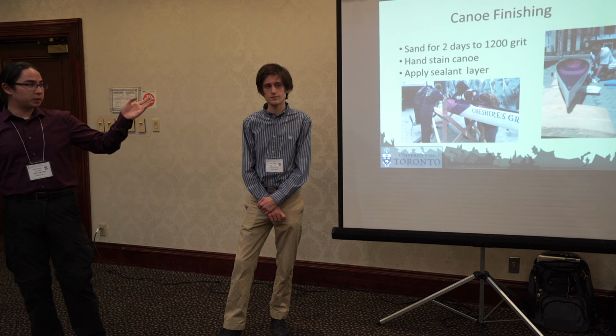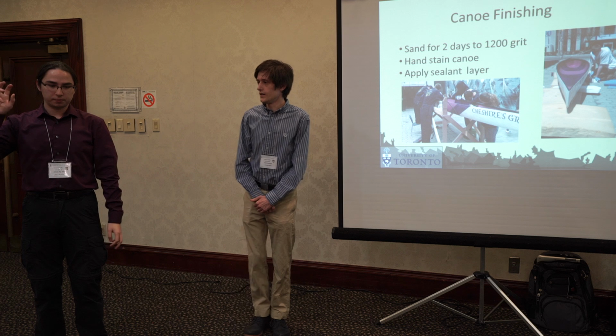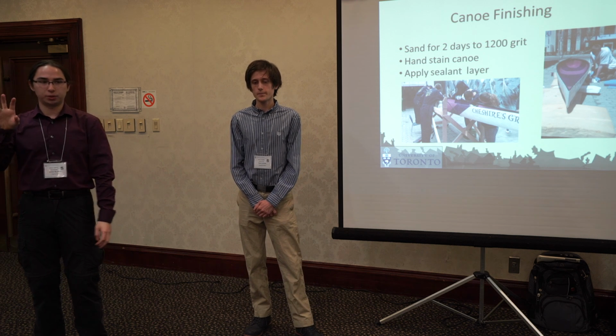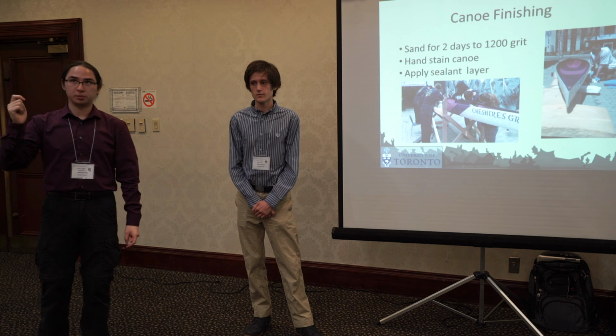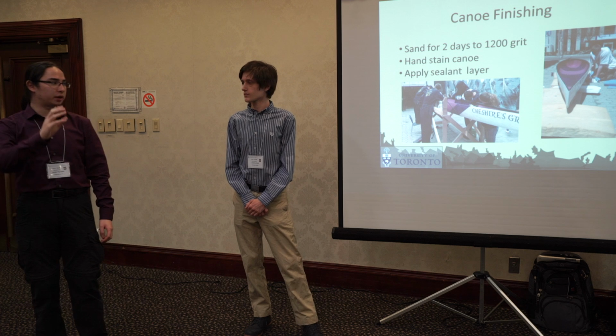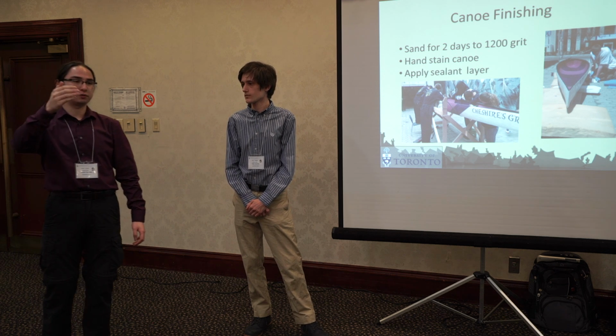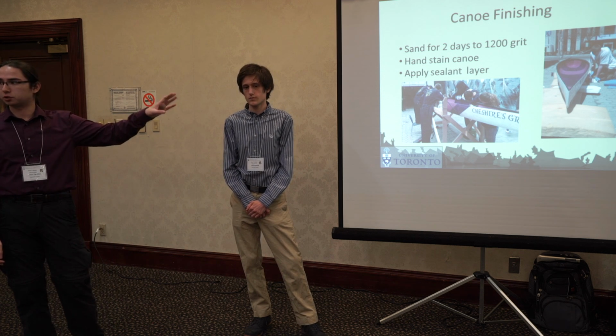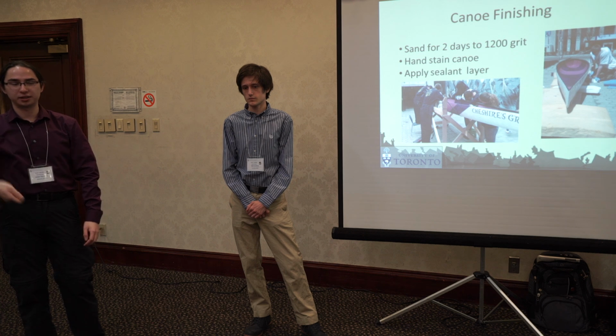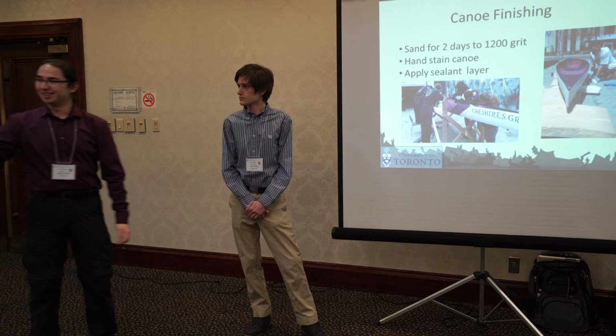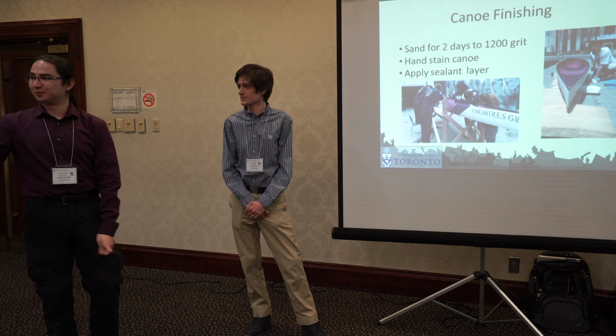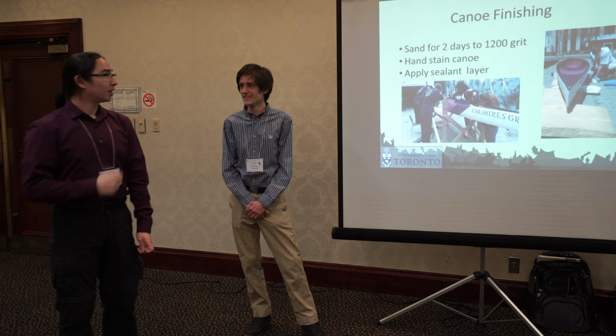We've also experimented with ideas of pigmenting an extremely low density mix, which would basically be just cement, and we'd have that as a sacrificial finishing layer on top of our structural mix. So we can just paint on this colored cement, which circumvents the rule because it's pigmented.